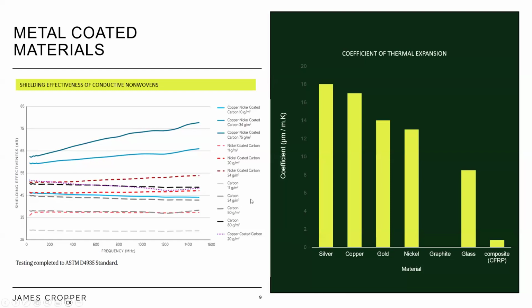On the right, we have a graph that shows the coefficient of linear expansion of certain materials. And the core benefit of using a non-woven fiber platform is that the coefficient of thermal expansion of the core fibers is similar to the coefficient of thermal expansion of the fibers within the composite. Our customers like this aspect as it reduces the repeat stress due to thermal loading. With that little summary, I'm just going to talk a little bit more about the electrical conductivity of our materials on the next slide.